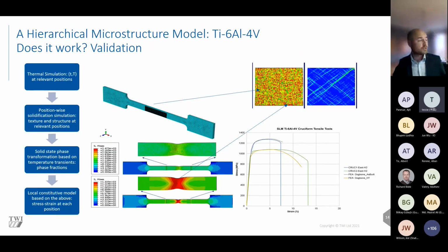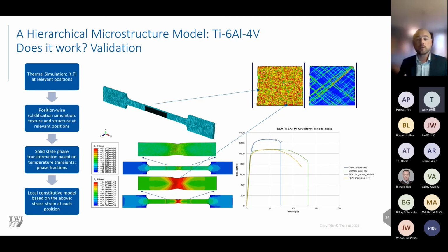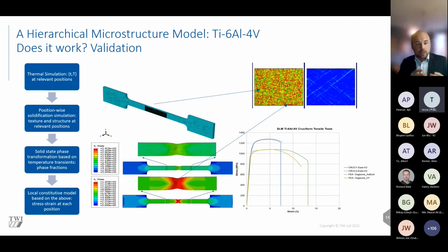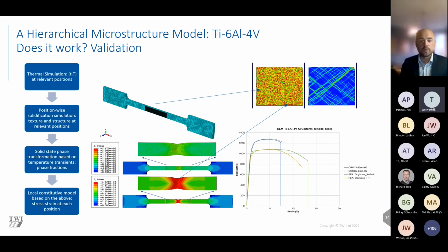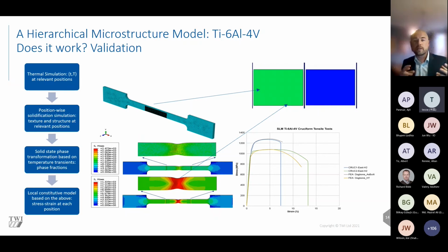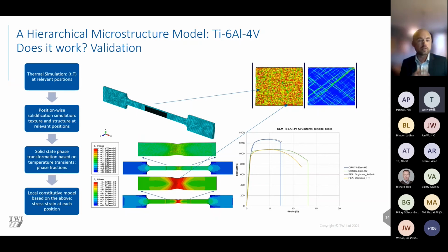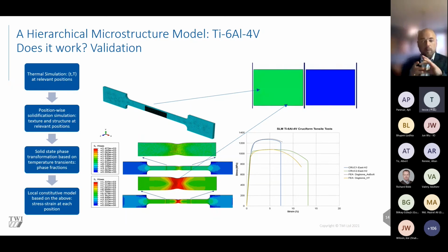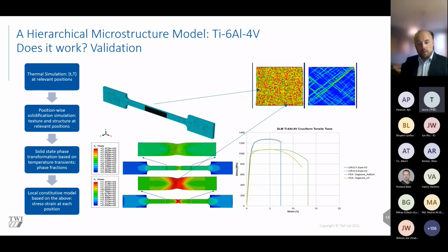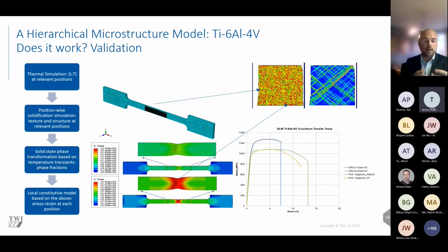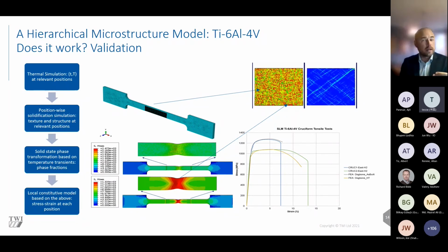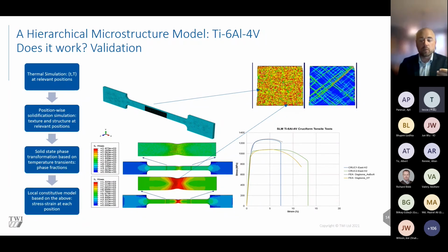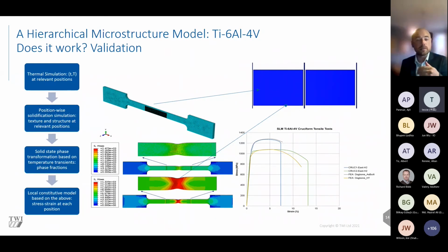So we can do these process simulations of the cruciform, dialing in just to the gauge volume of the dog bone specimen, removing that dog bone specimen with all of the nice tracking of the phases and the solidification structure. And then looking at those phases and the orientations and assigning them local properties. And then we can do the simulation of the tensile test and recover, within reasonable accuracy, the behavior that we'd expect of the as-built and the heat treated.